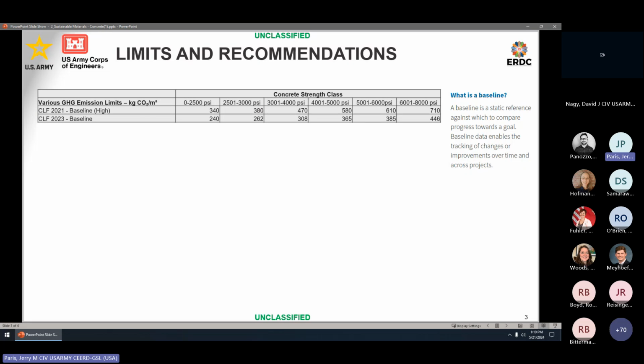And then 2 years later, they produced more baseline values, and they're dramatically lower. And they remove the definition of what they are considering a baseline. And what ends up happening is, for this data set, this baseline is actually representative of a 30% fly ash replacement, or removing 30% of the cement within a concrete and replacing it with a waste material. So that's why these numbers are considerably lower than the data set from 2 years prior.